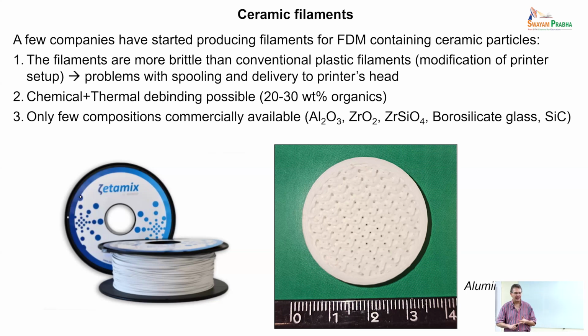So we're still talking about extrusion, either of a paste or of a filament, molten filament or molten pellets. And I mentioned that it's difficult to make these filaments, but this French company is able to make alumina, alumina zirconia, white and black. They make titania. They make low permittivity ceramics. They make silicon carbide, and they make ultra high temperature ceramic filaments. They just developed that. And we developed with them silicon nitride, but it's not commercially available yet.